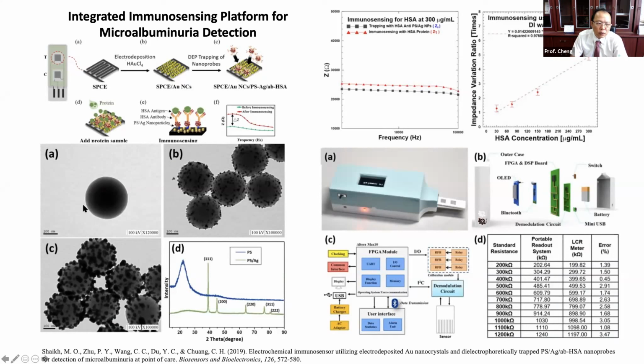But at this time we use polystyrene particles, and we use an electroless plating method, like you can see, silver nano dots on the polystyrene particle. Then after we immobilize them on this interdigital electrode, we can detect the protein in the urine. We also developed this readout circuit, and then we can have the portable device. You just insert your chip and drop your urine. One side is for the test side, another side is for the control side.